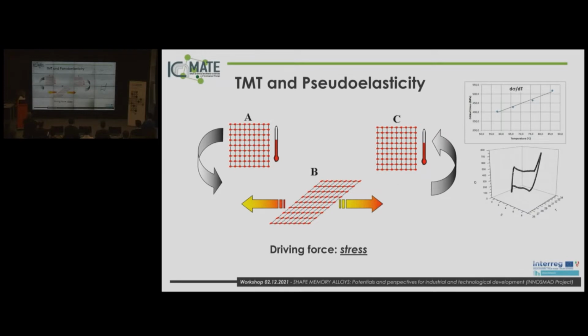When we consider pseudoelasticity, the phenomenology is related to inducing the thermoelastic martensitic transformation in isothermal condition, only by applying stress. In this case, we start from the austenitic phase, and then we go to the martensitic phase, only by applying stress. We apply force, the material transforms, goes to martensite, deforms in the martensite, and then when we remove the stress, the material comes back to the initial shape. The martensitic state shrinks, and then we come back to the austenite. In this case, we don't use the temperature, we use only the stress. But there is, in any case, a transformation.